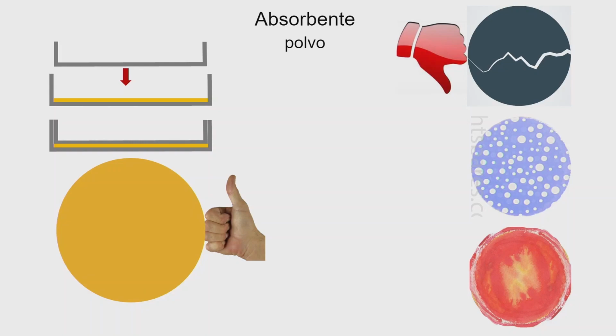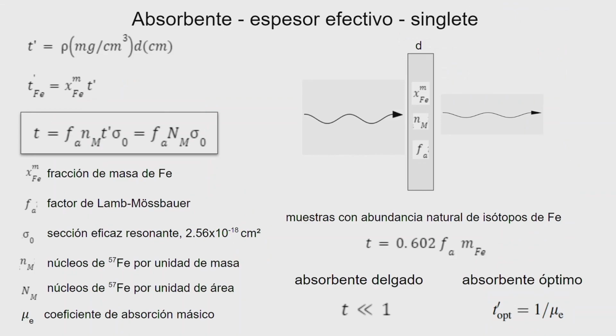And the more background you have, the more Poisson distribution you have also. So that the ratio signal to noise deteriorates. So the absorber should look as much uniform as possible. And then, well, there is a parameter, a quantity, which has been defined as effective thickness of your absorber, to which we have to put attention in order not to have distortion effects on your spectra.